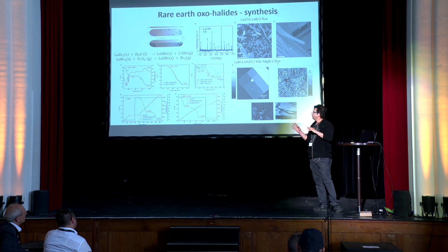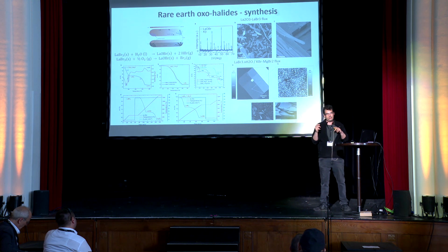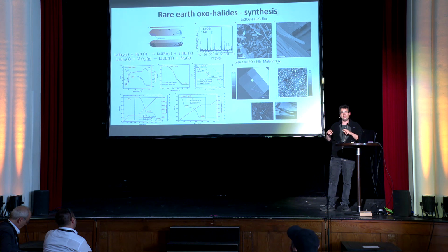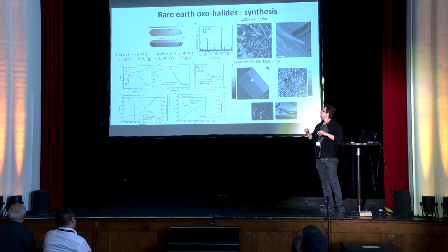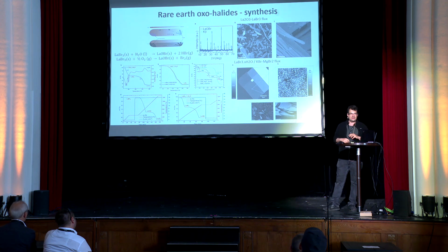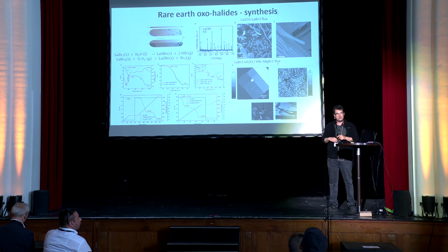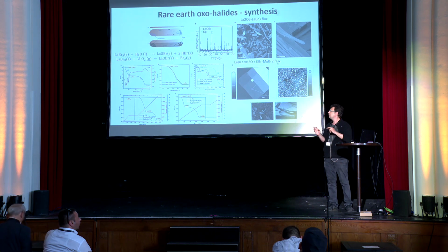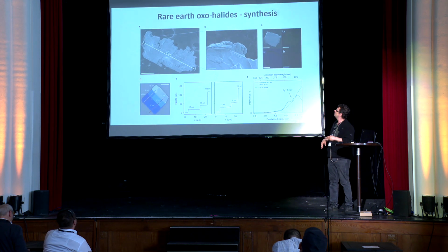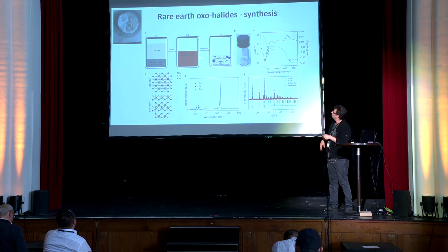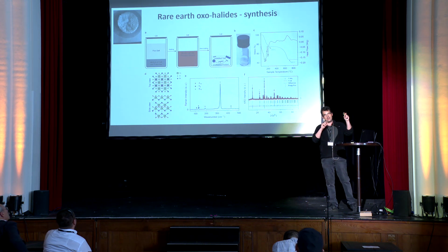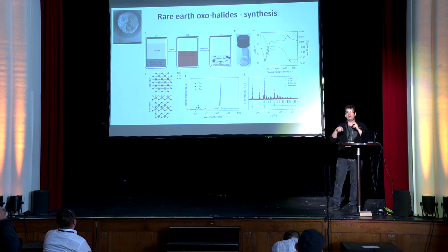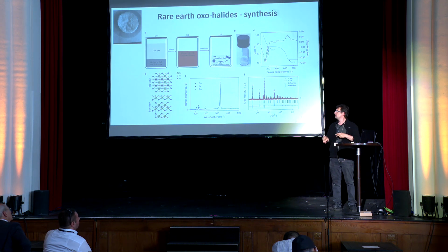But at Vienna Technical University, they are now trying low temperature AFM, so they try to condense some monolayer of water, and then they find some absorption. So definitely there will be, on the monolayer, atomic level, some interaction with water molecules. And by studying this using AFM, it can be found there are bromine vacancies, and also, depending on the flux used, like when we use a magnesium-based system, some lanthanum can be substituted with magnesium, and then it's compensated by a bromine vacancy to have a neutral charge in the system.